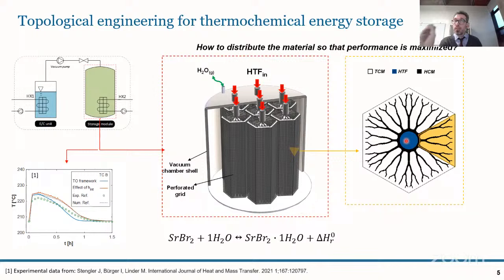Importantly, and a bit differently from the previous presentations on electrochemical storage, one of the other key performance parameters here is the temperature at which the heat is stored and retrieved, or in other words, sometimes also called the exergetic content of the heat stored. So the quality at which this heat is stored is quite important, and it's not only about extracting and storing heat effectively, but also extracting and storing heat at the right temperature that allows better end use of that heat.